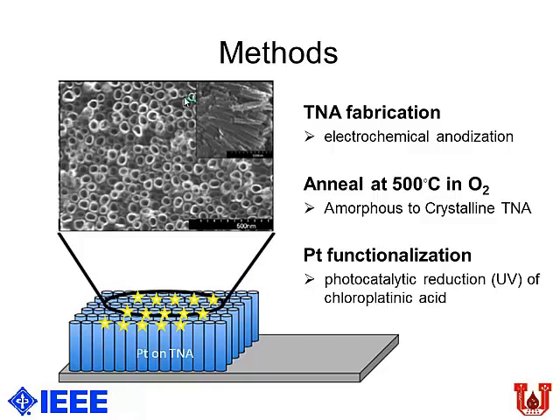You can actually control the length and the diameter of the tubes by controlling the time for which you anodize it and the voltage you apply. And subsequent to that, you anneal them in oxygen at 500 degrees C. This would change the structure from amorphous to crystalline. I'll explain why that is important. And subsequently, you deposit platinum on it. It's again a non-clean room based technique.